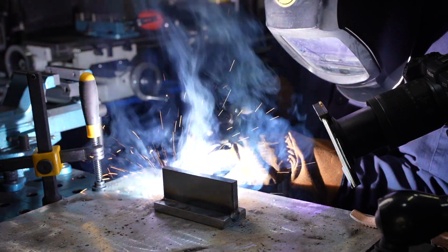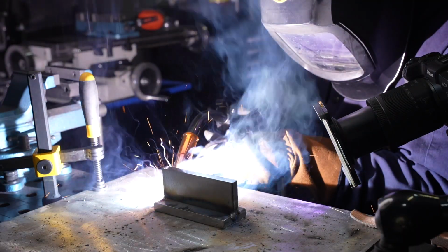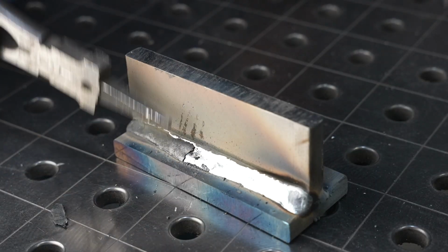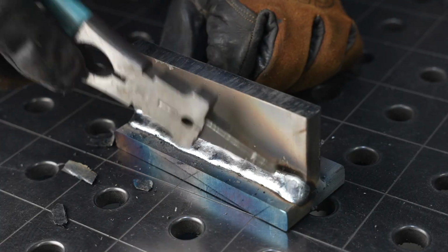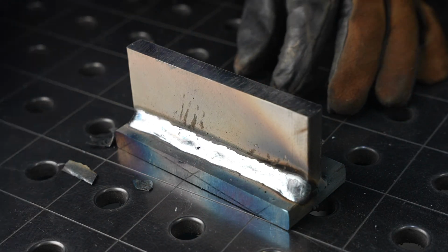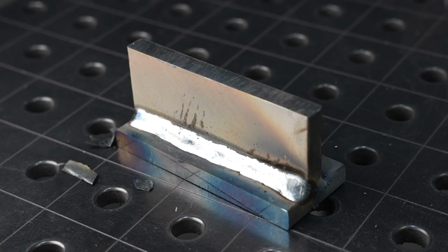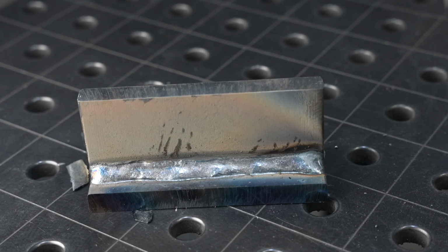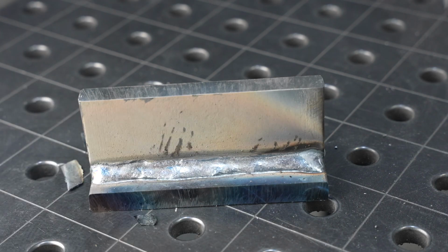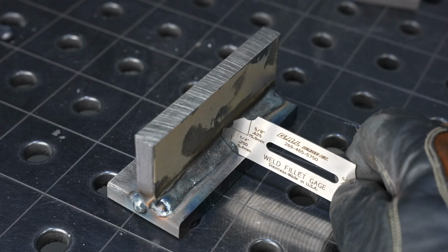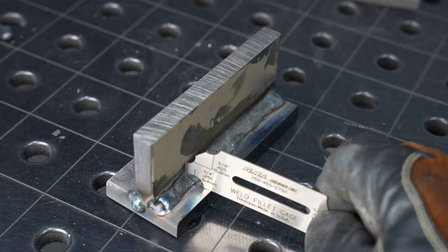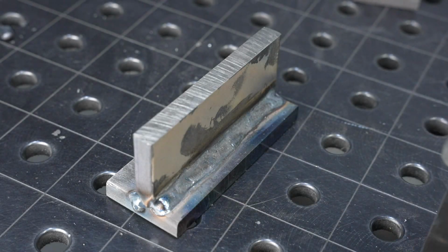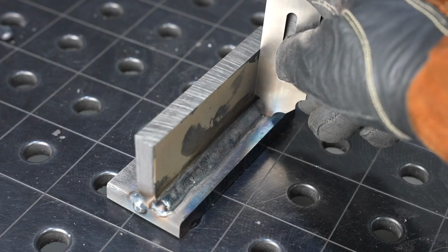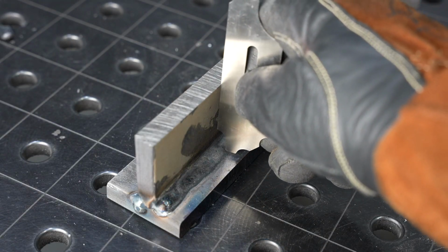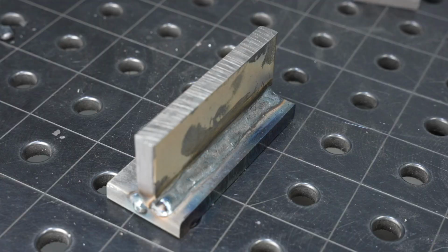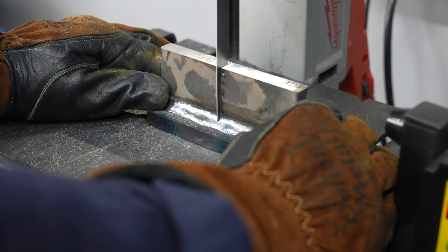Now, dual shield, it is a pretty runny puddle, and so it's pretty sensitive to any little movements that you have. So you'll notice there are a few little inconsistencies on that lower toe right there. The upper toe is pretty consistent, but any little movement, it's going to capture it. On the left, that looks like a little bit of undercut. I didn't notice any in real life, so I'm not sure if that's just part of the image or maybe there is a little bit there, but its size is right about 1/4 inch, and then on that lower leg about 1/4 inch on the smaller parts, and the bigger parts are just a little over, so let's cut it apart.